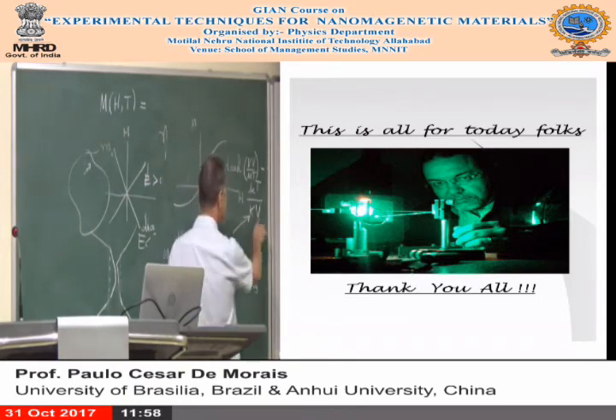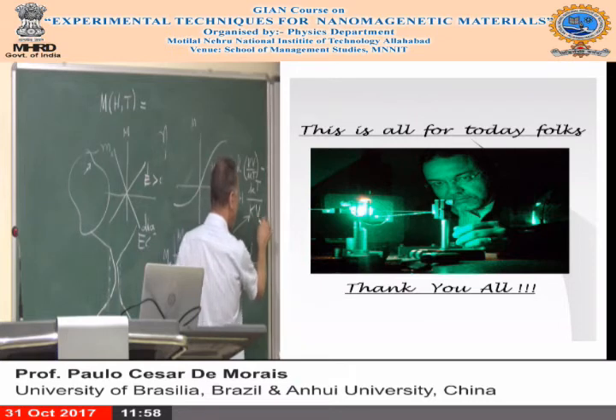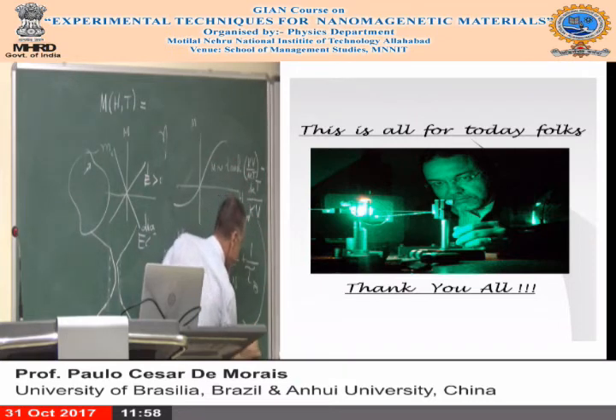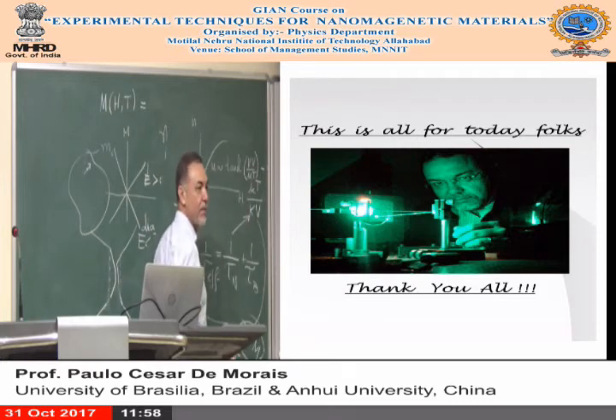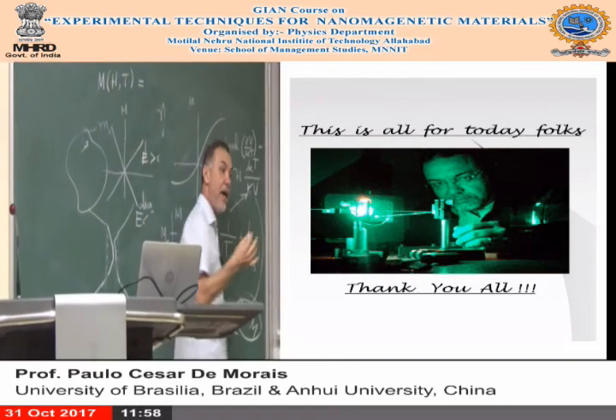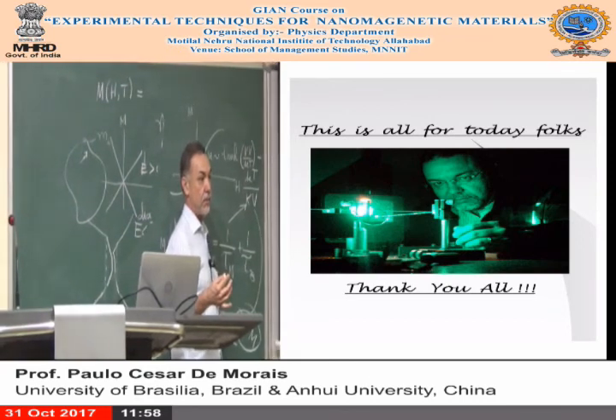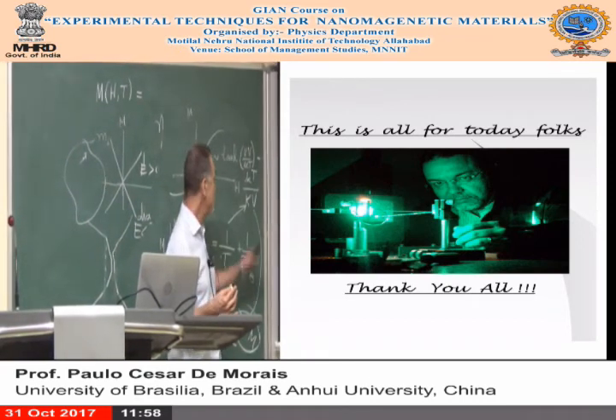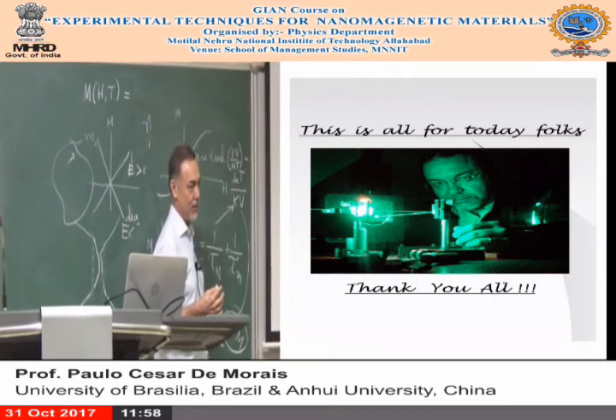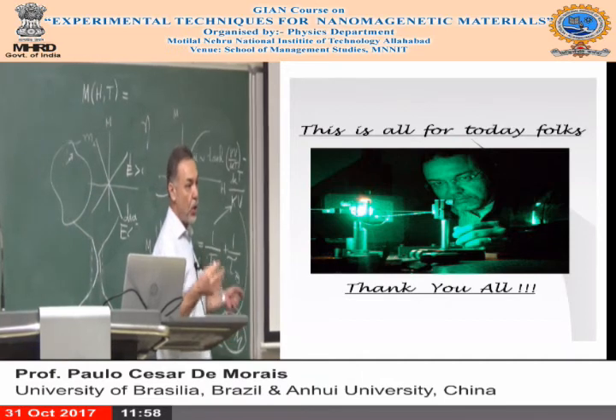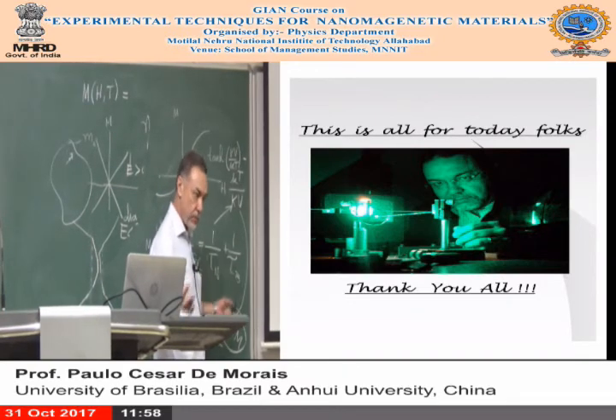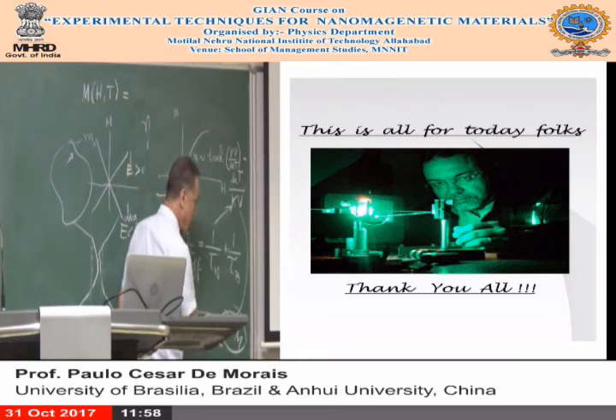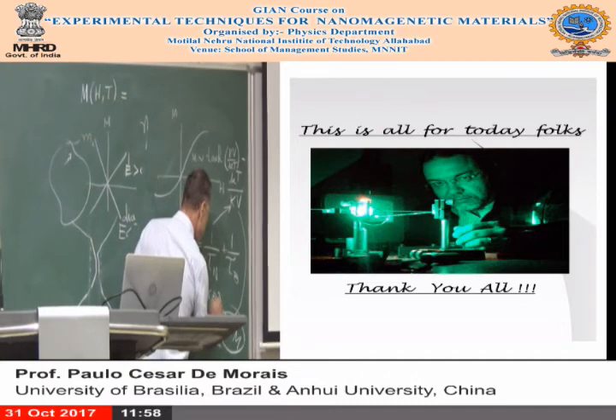But you need to know about this one, the volume. So how do you know about it? Make TEM. Then you can include here the average size. Is it physical volume or magnetic volume? This is magnetic volume. Well, magnetic volume is close to physical volume. So you can double check this volume by doing TEM and X-ray diffraction at the same time.